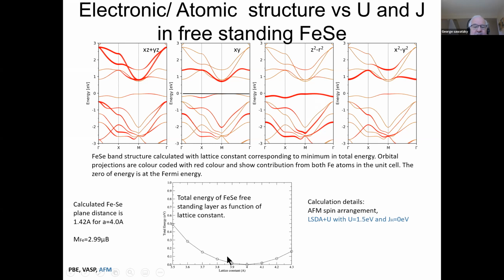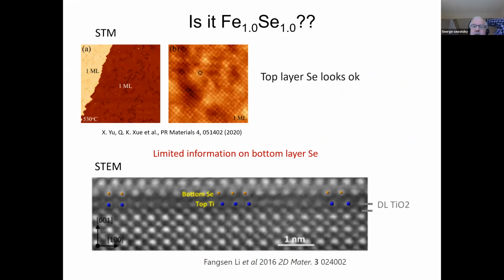Again, the lattice constant now is very large. It's 4 angstroms. And when you stretch things out horizontally, the vertical distance will decrease also, okay? So in the non-magnetic material, if you had this kind of lattice constant, the selenium would be much closer to the iron plane. But actually, the distance now is 1.42 angstroms, which is much larger than if you use a Poisson-like ratio to determine what that distance is, which would be more like 1.30 or 1.28 angstroms. Okay, so again, a larger magnetic moment gives you this very huge change in the selenium to iron plane distance.